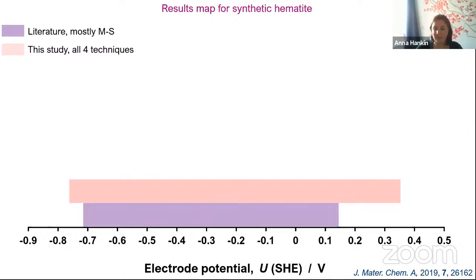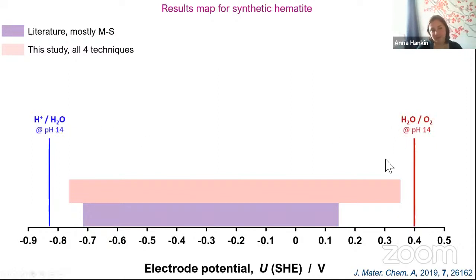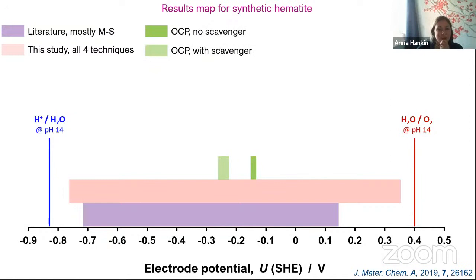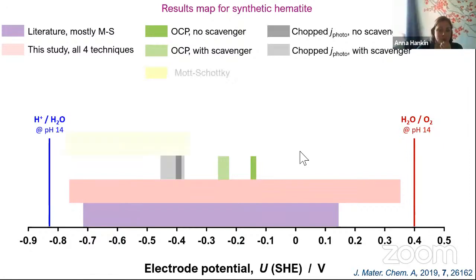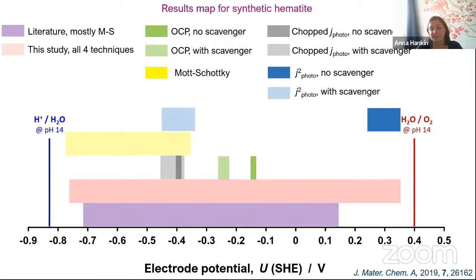So on here I superimposed the actual potentials for water splitting, the two half reactions. So you can see the staggering problem. And then I went through all the different techniques and just to report what I observed with each one under different conditions. And so you can see, again, without going into detail, the enormous spread that actually results. So the main conclusion was that the Mott-Schottky has so many errors, and you have to take into account so many effects, that it's not actually the best thing to do. But at the same time, multiple techniques should always be used going forward to determine this value, if the published values are actually going to be sensible and useful to someone else. And so you can see the huge problem here.